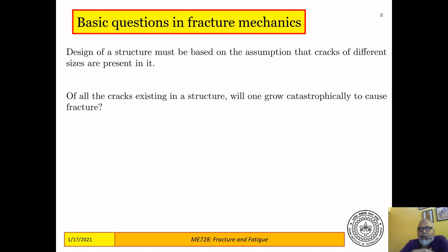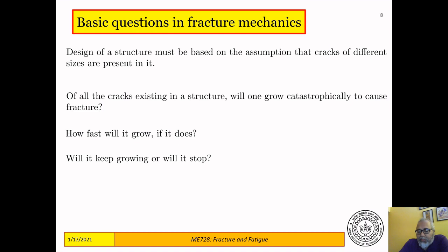Now, the question is, of all the cracks that exist in the structure, will one grow catastrophically, or will all the cracks remain dormant? If all the cracks remain dormant, I don't really care, because it's not going to fail the structure. But if there is one crack in some location which is able to grow catastrophically, then my structure fails, and I have to be wary of that situation. If there is one critical crack in the structure which can grow catastrophically, then I have to further ask the question, how fast will it grow? And will it keep growing, or will it stop?